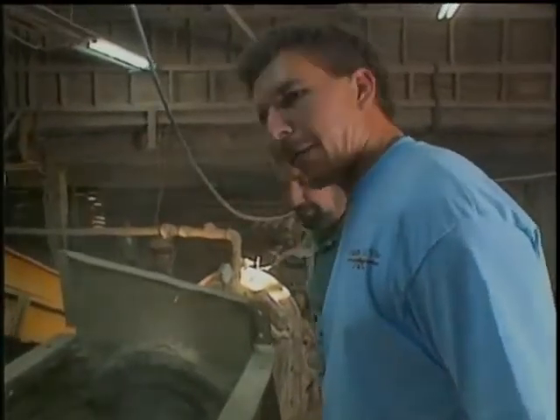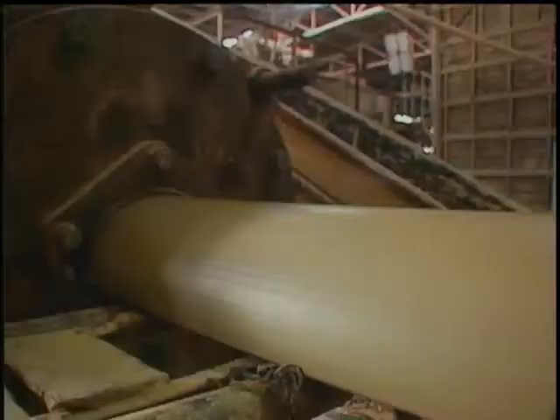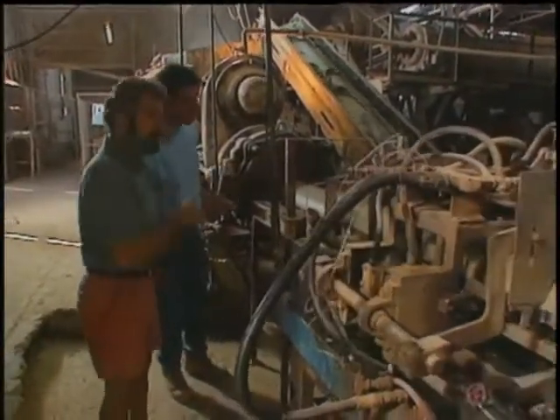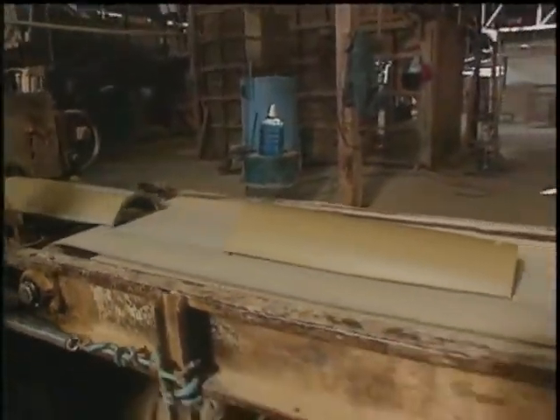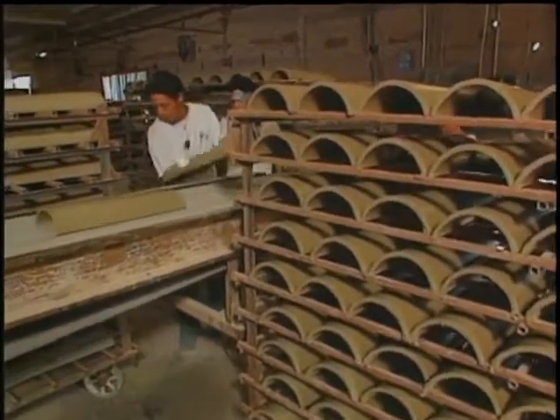You've got the material down to a fine clay — now what happens in here? This fine clay will be transferred to this hopper, mixed with water, and pushed down into the vacuum chamber of the extruder machine. This is pretty old equipment. You can see the tile coming out of the extruder. We're making the two-piece right now, but we can change the die to any type — the Baja Mission, the S-tile, the lightweight S-tile. The shape of the die determines the cutter, and the machine tapers the end of each piece. All the waste clay goes right back into the hopper — we recycle all the clay. From here they go on racks and are taken all the way to the drying rooms.